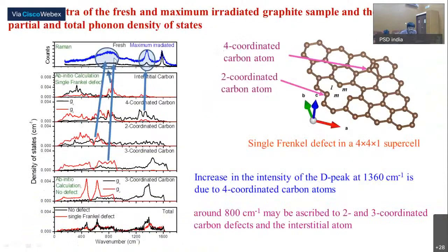To understand this additional intensity in the Raman spectra, we also calculated phonon spectra. When one atom is knocked out, we can see that this atom is 4 coordinated, this is the interstitial atom, and this atom is 2 coordinated. So now we have a structure with 2 coordinated, 3 coordinated and 4 coordinated atoms. For each of these 2, 3, 4 coordinated structures and this interstitial atom, there is a different density of states because the interaction would be different.